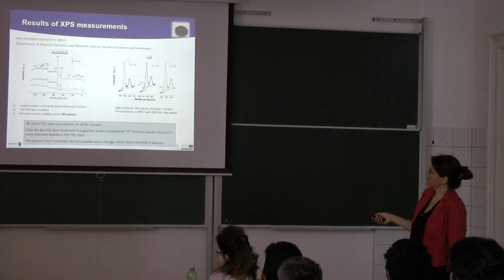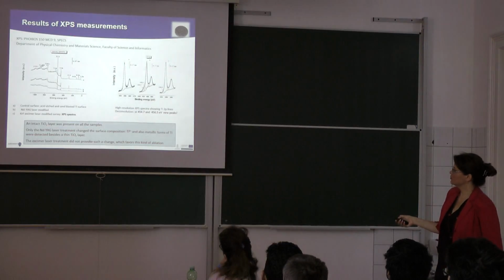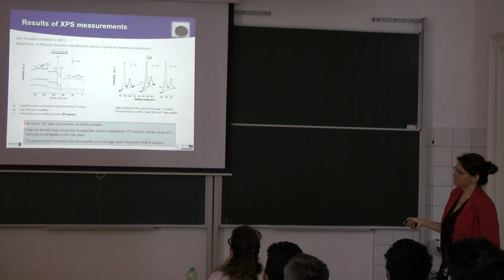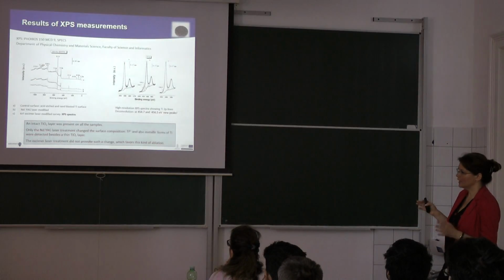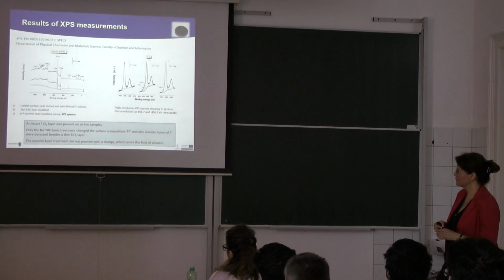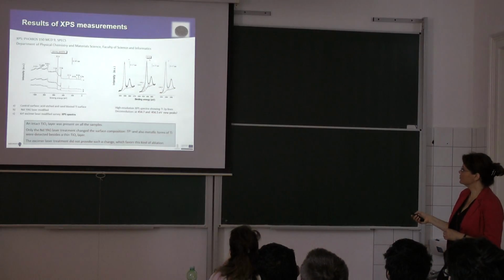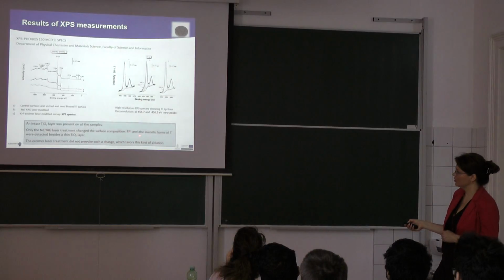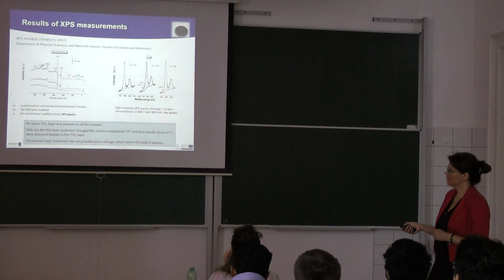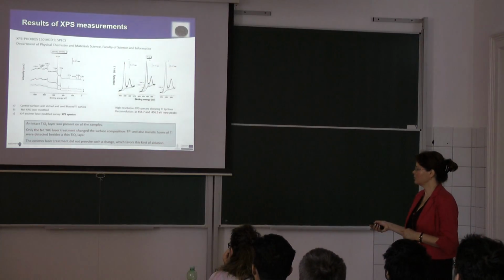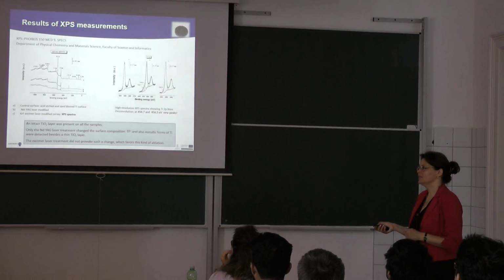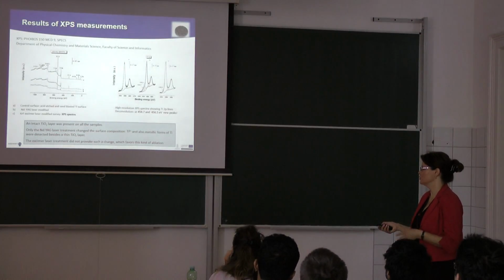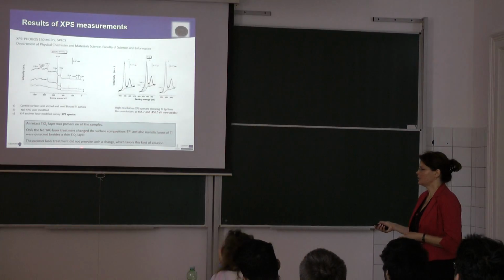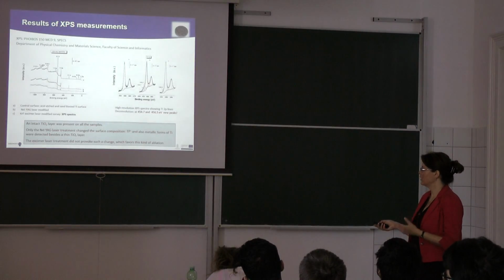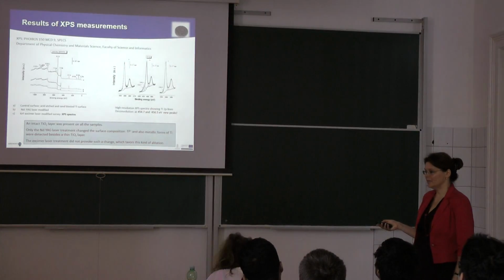The XPS measurements, this is the overview of XPS measurements, show that the native titanium dioxide layer is intact, but the neodymium laser treatment changed the surface composition, and we also found metallic titanium and titanium 3 plus components between the titanium dioxide layer, which means that neodymium laser treatment is not so good for that. The excimer laser treatment did not provoke such change, so we would favor this kind of ablation if the excimer laser would be so